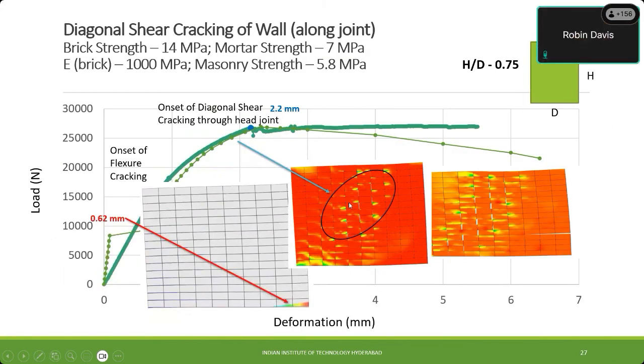Okay. And here, if you see this one, it is very nicely matching overall. Correct. But how is that comparison with experimental? I forgot to show you that. So we did not. The experimental data for in-plane here came from someone else's test. We didn't do the in-plane. We did it for compression, and we did material level tests from which we extracted material parameters, then put them into a finite element model for a structural scale, which is basically a wall. This is a physical wall of a certain dimension, and we used that to predict and match with the experimental data for that wall.